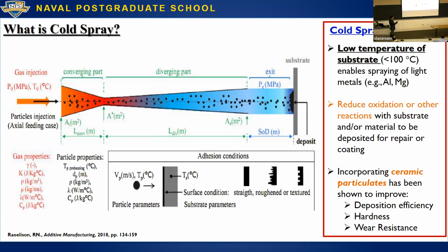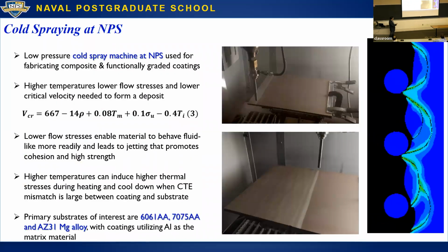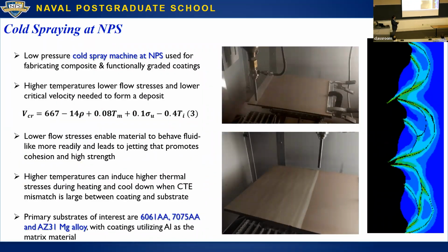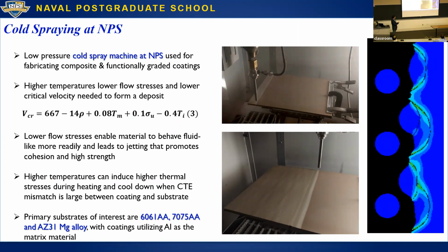And they form this deposit layer by layer, where each layer is essentially made of several powders that have been impacted onto that substrate. And we do know that when we incorporate ceramic particulates into the process, we can improve the deposition efficiency, the hardness, the wear resistance. So what we're trying to do is really get, and this is a schematic, a simulation of what the process looks like.